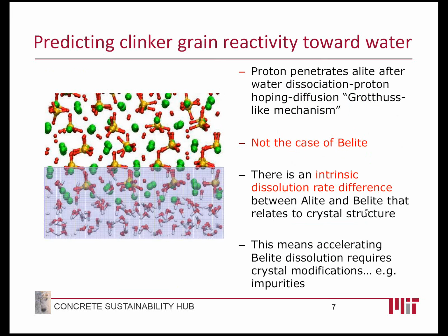Okay, so this is a molecular simulation of the dissolution of alite. At the bottom of this plot on the left you can see water molecules coming close to the surface of alite. We found out that the water molecules, or at least the first water molecule that comes close to the surface, dissociate, and we have a proton penetration inside the structure. This is a hopping diffusion mechanism known as a Grotthuss-like mechanism. What is very important is that this is not the case for belite. So there is an intrinsic dissolution rate difference between alite and belite, and that relates to the actual pristine, original nature of those crystals. The second consequence is that if we want to accelerate belite dissolution, we need to modify belite, for instance by considering impurities in the crystal. Next.